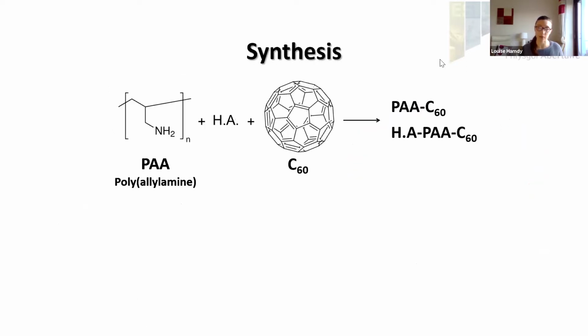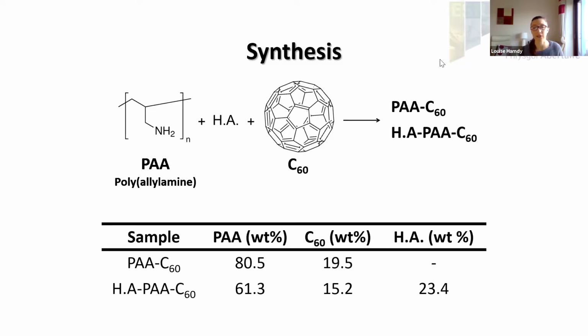The material that we made was a polyallylamine, which only contains primary amines, which are generally the most effective for CO2 adsorption. This amine is combined with a hydrophobic additive and cross-linked with fullerene C60. We made the adsorbent with the additive and without the additive, PAA C60 and hydrophobic additive PAA C60. We use elemental analysis to determine the percentage weight of each component of the materials. We see that the hydrophobic additive accounts for about 23% of the weight of the additive material. And importantly, the hydrophobic additive material has a relatively less weight percent of amine.